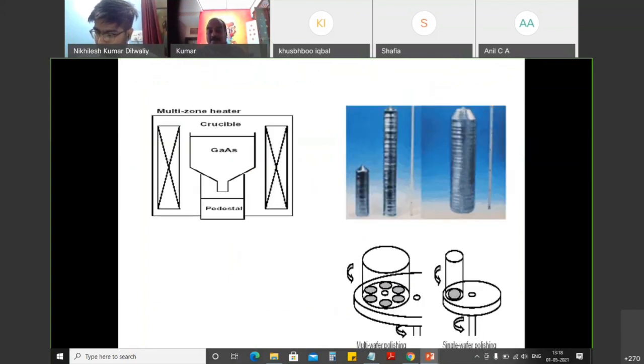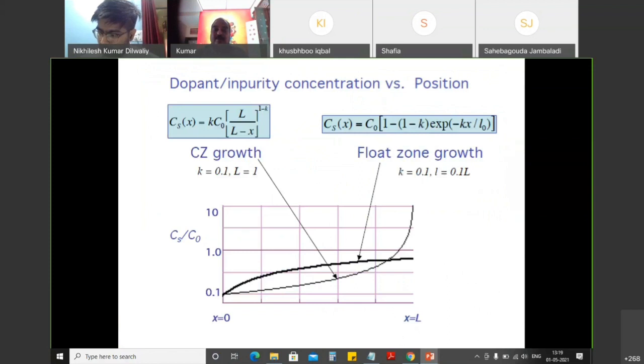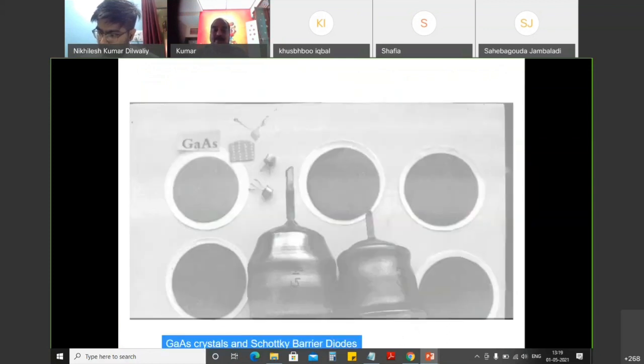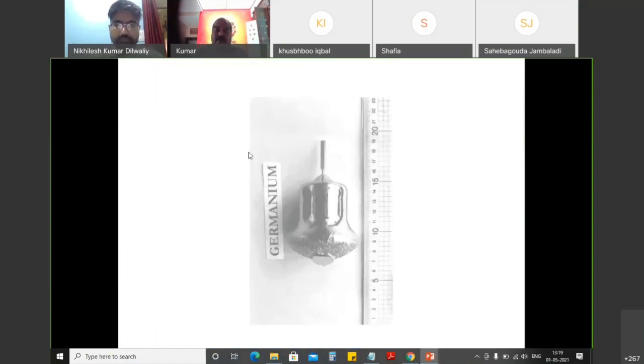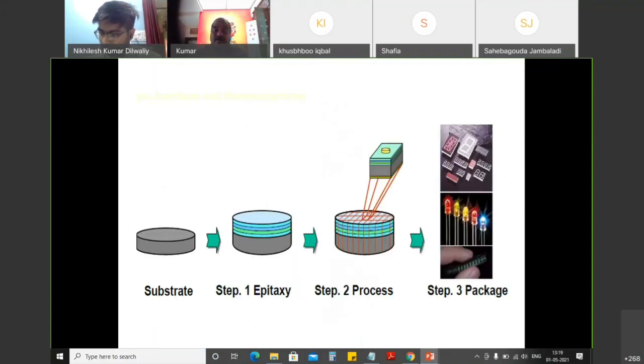This electronic grade silicon, as you see here, can be grown in large sizes, more than 600 kilograms, and something like 12 inches in diameter. Initially, they grew only millimeter or 1 centimeter diameter. Now they are growing 12 inches in diameter, and these are being used for subsequent polishing and then fabrication. These are some of the gallium arsenide crystals which I grew in the 1990s, and I made use of them to make solar cells for space applications, which I tested in Italy. And these are some of the germanium crystals grown once again for our ISRO. On top of it, we can grow gallium arsenide and use it for device application.